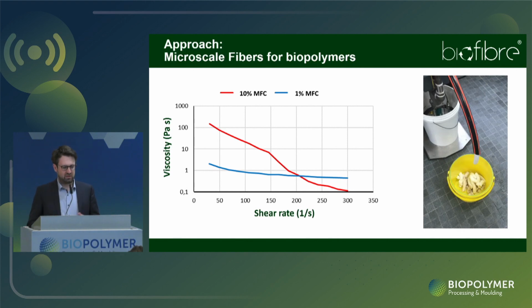But when you come down to the nanoscale fibers, some of you know already that those nanoscale fibers are largely shear thinning. It means that it behaves like a solid if it's at rest or you don't move it. But once you are moving it through screws, through different mechanical forces, then you can really make it into a stage that it's behaving like a liquid, and it gets even more prevailing if you enhance the solid content. So pretty much the stage of 1% solid content is something like you can compare with oil, or let's say something like a jelly material. But if you talk about 10% MFC, you really already talk about, let's say, at least a chewing gum, and when you go up to 30% MFC, you don't believe that this can be flowable just by shearing forces.